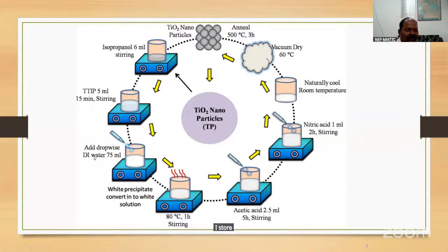and stir this one, add dropwise distilled water 75 ml, white precipitate. Now stirred, then acetic acid 2.5 ml, 5 hours, stirring, nitric acid 1 ml, 2 hours stirring, naturally cooled to room temperature, and this is vacuum dried at 60 degrees Celsius. Then the material is annealed at 500 degrees Celsius for 3 hours, and we got the titanium oxide nanoparticles.